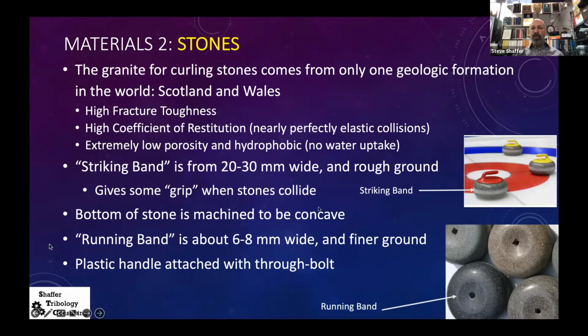The bottom of the stone, as we saw, is machined to be concave here. And the running band, again, is 6 to 8 millimeters wide, and it's finer ground, not super fine, finer than the striking band for sure, but it's ground with, say, 80 to 100 grit paper. And then there's a plastic handle they mount on top. There's a through hole and a bolt that comes up through the bottom that's in this countersunk hole here.